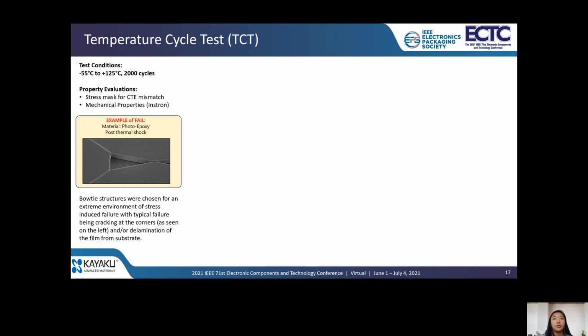So temperature cycling was also completed with photo patterned structures, really to test the CTE mismatch and overall resistance of the material to exposure of extreme temperatures. Thermal mismatch of polymer to substrate or metal can cause stress-induced failure, such as solder joint cracking, warpage, or delamination. PRL-29 has a CTE of around 60 ppm per C, compared to silicon, which is around 2.6. So to offset this value, PRL-29 has a low internal residual stress value of around 14 megapascals, along with that good balance of mechanical properties as we've already proved previously.